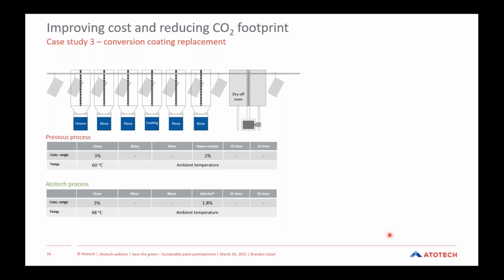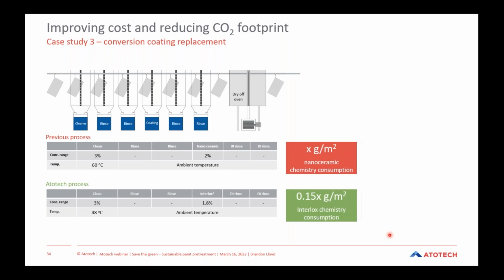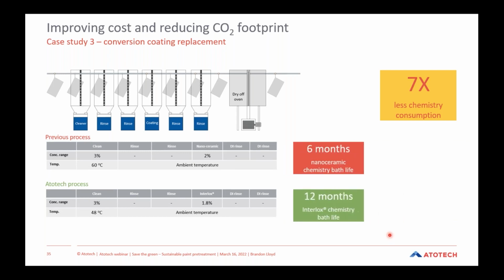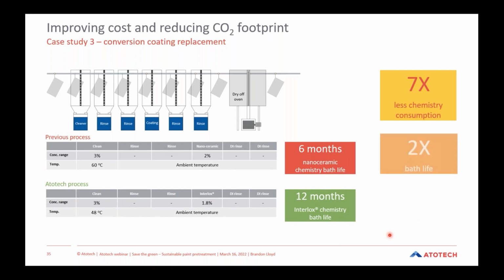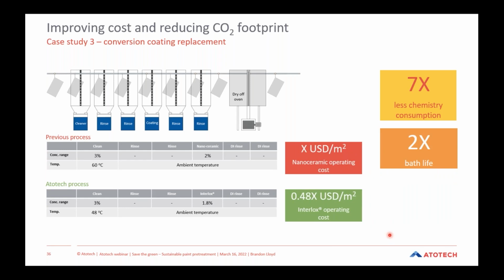So here you can see the process differences from the 2 applications. With the conversion from the nano ceramic to Interlox, we were able to reduce the chemical consumption by quite a bit. A total of 7 times lower chemical consumption for the applicator. We were able to extend the solution life from 6 months to 12 months, which is a 2x bath life extension for the applicator. And then lastly, we were able to reduce the operating cost of the pretreatment itself as well by about 52%.